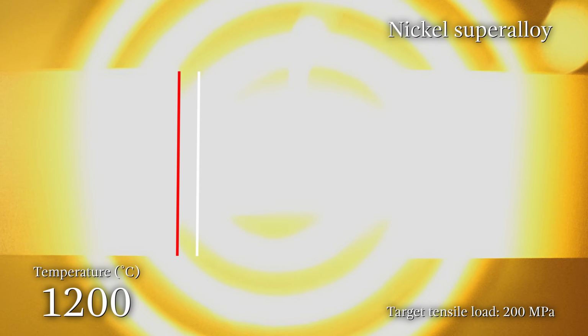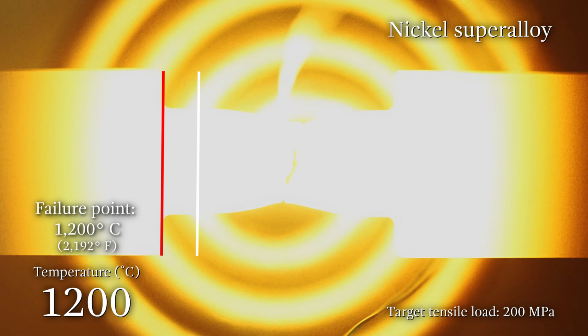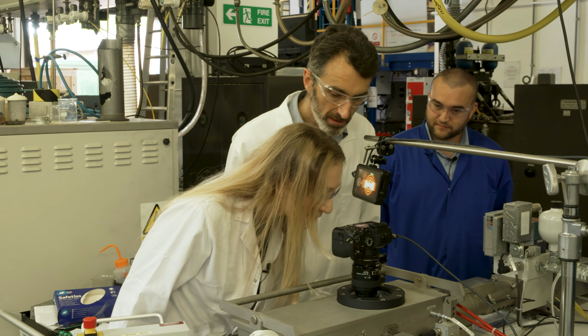But if you push the temperature too far, even this alloy reaches its limits. Cross-slip becomes easier. The paired dislocations can now hop between the planes together. And the ordered cubes of gamma prime start to dissolve, so the dislocations break free and it finally gives out. Oh, it may have just, did it break? Oh yeah, it did, it broke.